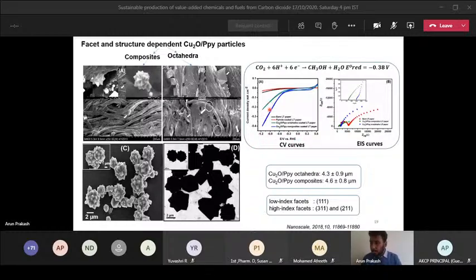Also we confirm this by using impedance analysis, and the conductivity is much better for the composite one rather than the octahedra one. So you can observe here there is no semicircle in this region for our composite paper, and the size of the particle is around 4 to 5 microns. It's not a nanoparticle, but still the activity is good because it has high index facets like 111, 311, and 211. So when you make a nanomaterial, micron or nano-sized particle, if you have defects like zigzag edges, or some high index facets, then you can increase the activity because you are lowering the adsorption energy of hydrogen or CO. That's why you are getting higher selectivity.